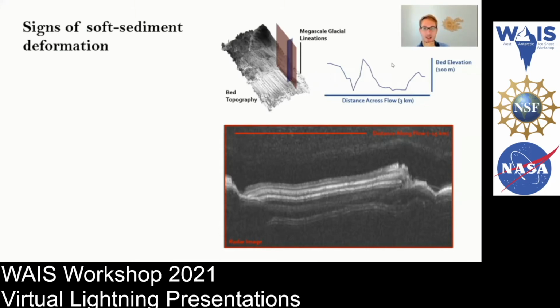One thing that we see is that in areas where we have lineations, which we interpret as soft sediment deformation, it appears in nadir radar imagery as these parallel lines within the subsurface reflector. So you can imagine this blue curve up here is the cross-sectional topography. If we're flying into and out of the page, you get reflections off of all of the peaks. And if you're flying in the orientation of those lineations, they appear as these repeating reflectors in a nadir image.